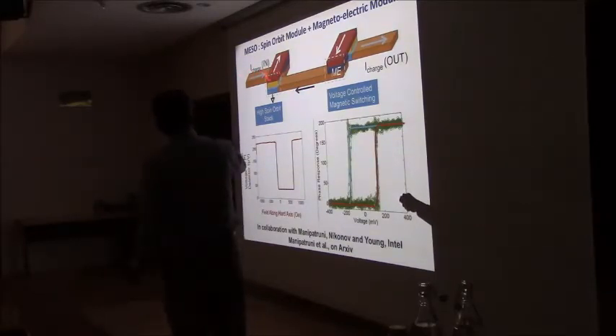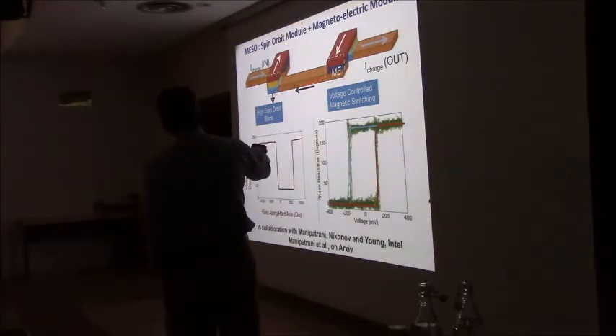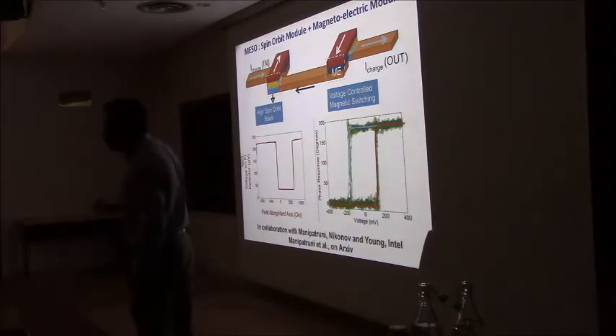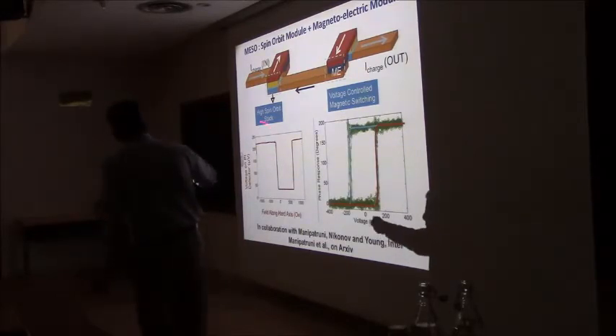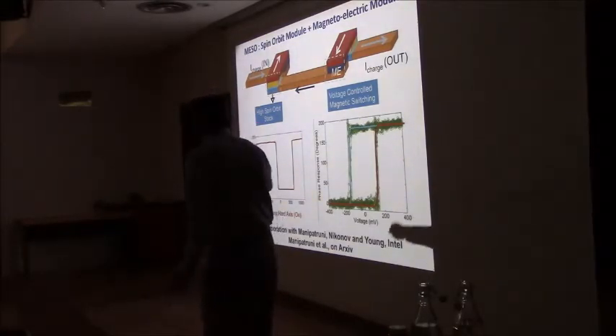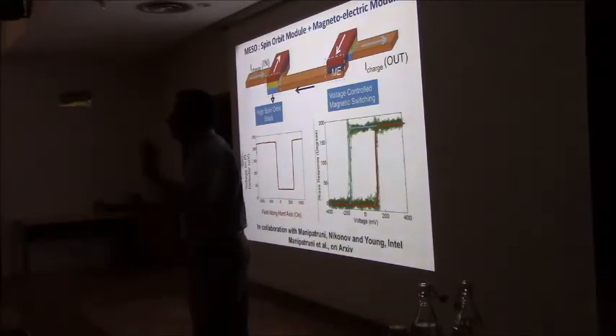On the left side here, you put in a charge, you do some operation, then you convert it back into a charge. There's a spin-orbit coupling stack, or the inverse Rashba-Edelstein effect stack, which converts it back into a charge. That charge is going to give you, hopefully, an output of the order of 100 millivolts. Keep in mind, this is all theoretical calculations. Actual data shows of the order of a few millivolts, maybe 1 to 2 millivolts. How to get that output signal from here up to 100 millivolts itself is going to be an interesting challenge, not trivial. We're assuming that our spintronics colleagues will do that.